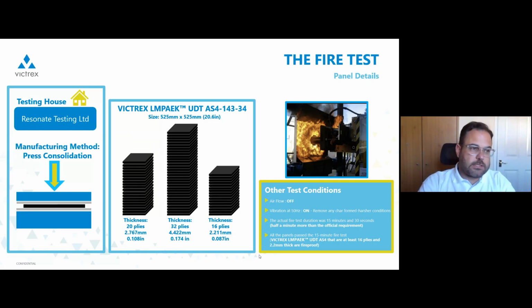And what the vibration does is quite common. When you do a fire test and your front face starts burning, then you produce char. And that char actually stays there and creates another protective layer. But when you introduce vibration, it's like a shaker table that you have your panel on, that will produce enough forces for the char to fall off. So you are again exposing the next layer behind. What I'm trying to say is, with vibration on you're actually making the test harsher, because you don't have that char layer at the front face.